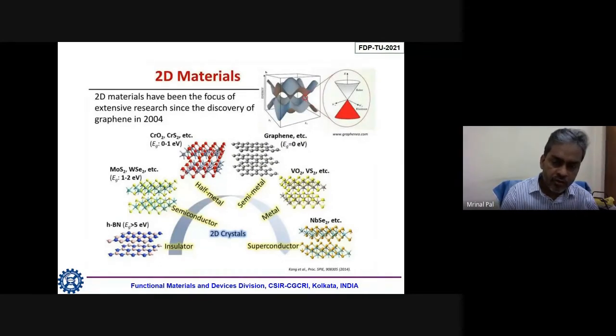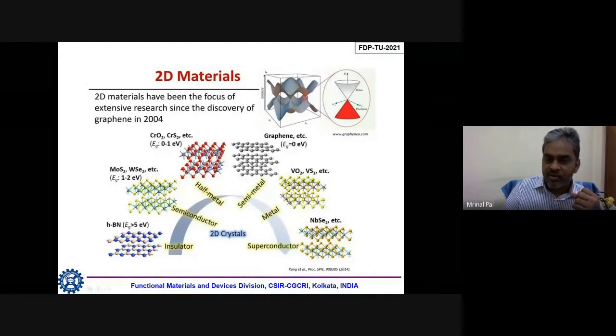Now, if you look into various kinds of 2D material, particularly from the electrical point of view, 2D material can be an insulator as well as a superconductor. Starting from hexagonal boron nitride, which is an insulator, to molybdenum sulfide, they are semiconductors. Also, chromium oxide is half metallic. Graphene, which is the most important and most talked about 2D material nowadays, is a semi-metal. Then vanadium oxide and vanadium sulfide are metals. And a material like niobium selenide shows superconductivity also. So by using 2D materials of different types, you can complete the electrical spectrum from insulator to superconductor. That is also one important aspect.